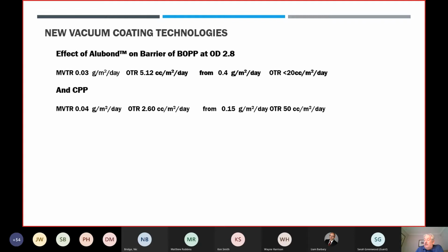And for CPP, you might decide that you're going to put a 2-layer structure together, and you want CPP as your sealant layer. So here's some information on the effect of AlOx on CPP. Again, a dramatic improvement in the moisture barrier, and an even bigger improvement than on BOPP for the oxygen barrier. And when you look at what it's come from, that is remarkable. And certainly a CPP with that sort of level in a BOPP laminate structure would give you very, very good barrier and almost close to foil performance, if foil was absolutely pristine, which we know in reality that there's an operating window and sometimes it's not quite where it should be.